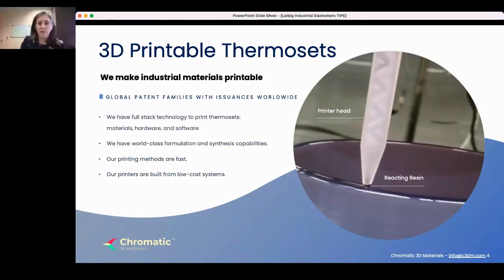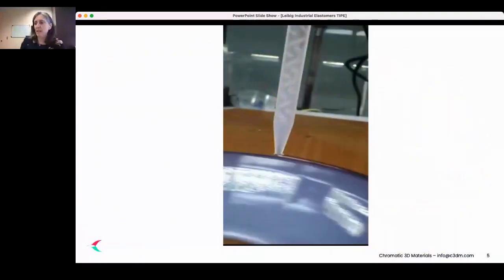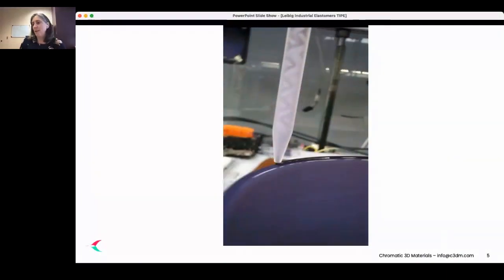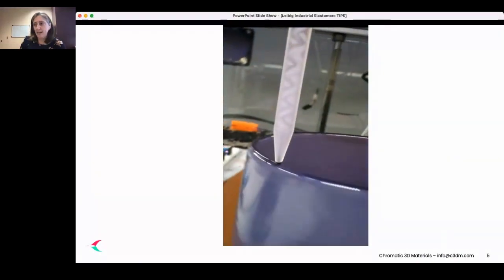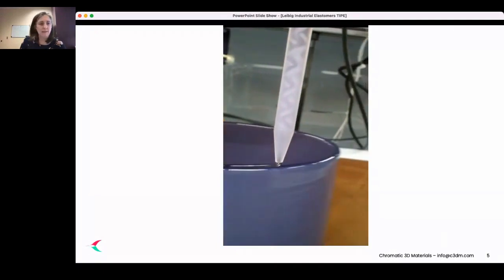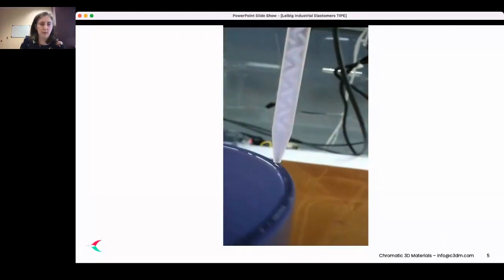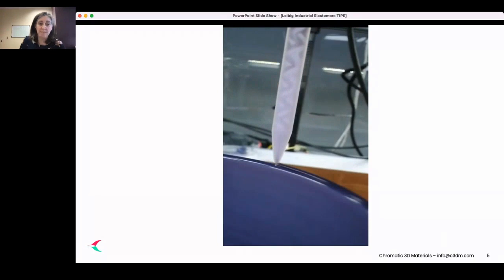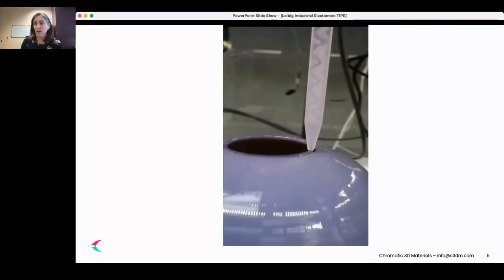And here's an example of the printing process. Here we're demonstrating what we call smooth mode printing, where the bead size is much bigger than the actual resolution size and smoothness of the print. We're able to build very high overhangs. We can do wall thicknesses that are anywhere between half a millimeter and larger, so we can do very thick parts.